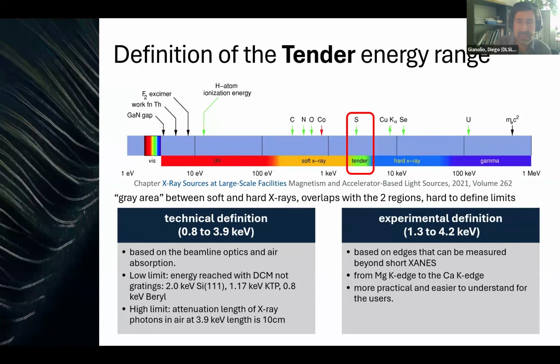So if we just limit ourselves to the silicon 111, then the lower limit would be at 2 keV. But there are several beamlines that use other materials, such as KTP, potassium titanyl phosphate, or beryllium aluminum silicate. And in this case, we can push the lower limit down to 0.8 keV.